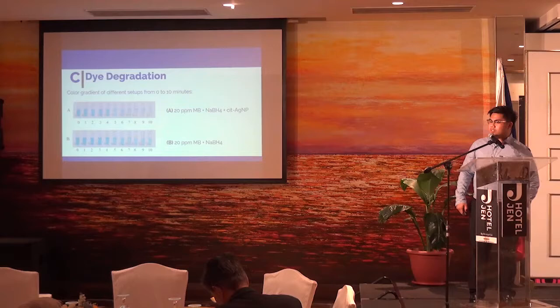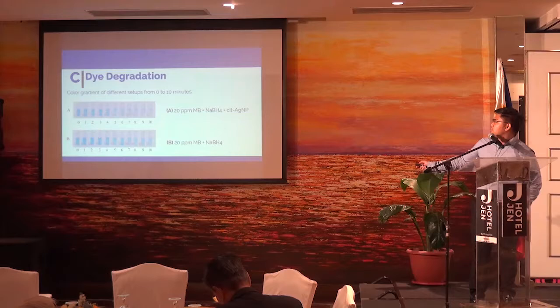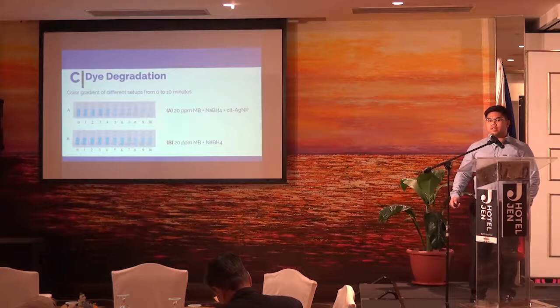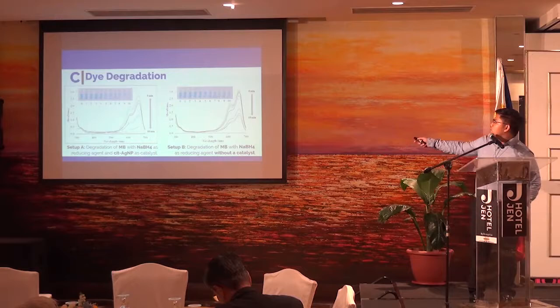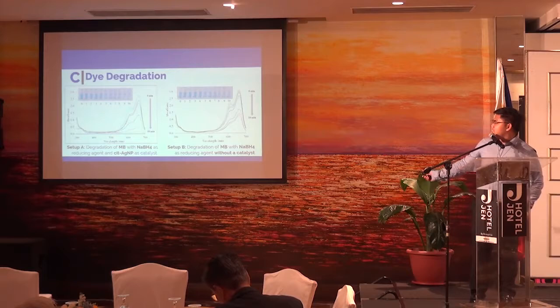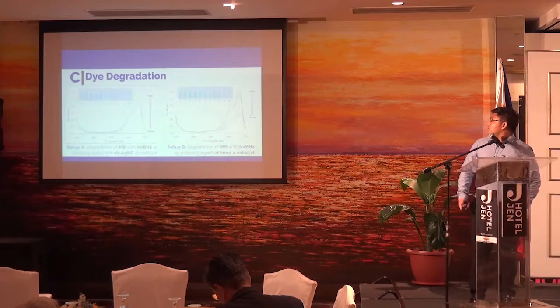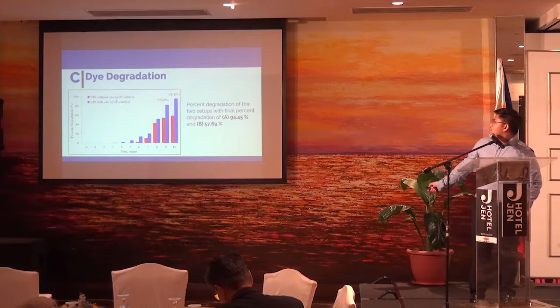Setup A is the setup wherein a catalyst is present in our vials; Setup B has no catalyst. As we can observe, in Setup A, from 0 to 10 minutes, on the 10th minute it is almost clear or white in color. Setup B, without catalyst, is slightly bluish in color. To further prove our degradation, we present the absorbance spectrum from the initial to the 10th minute. For Setup A, the graph at the 10th minute is almost flat, meaning nearly zero absorbance. For Setup B, there is still a remaining methylene blue concentration. Comparing the two setups, we obtained 94.45% degradation for Setup A, and for Setup B without the catalyst, only 57.69% degradation.